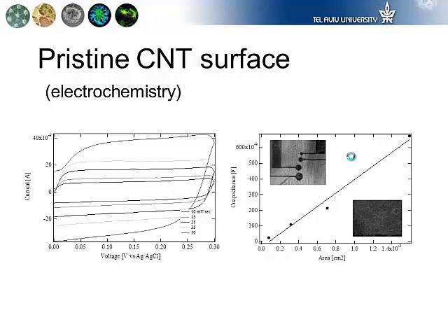The important thing, though, is that even though I showed it as if it's quite trivial, it's not at all trivial. The major challenge here was how to avoid clogging the entire film by the polymer. Since the polymers have to be insulating, there's a very tricky trade-off. There's actually a great amount of detail in how you deposit the polymer and how you remove it.